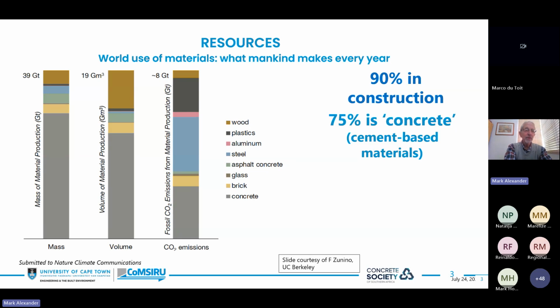And you can see, obviously, if you look at volume, timber occupies a much larger slice because of its low density. But when you start to look at the CO2 emissions, the picture immediately changes, and steel jumps right to the top of the pile, as you can see there, in terms of the CO2 emissions from the steel. So the CO2 emission per kilogram of steel is very high. And concrete takes a lower profile here.